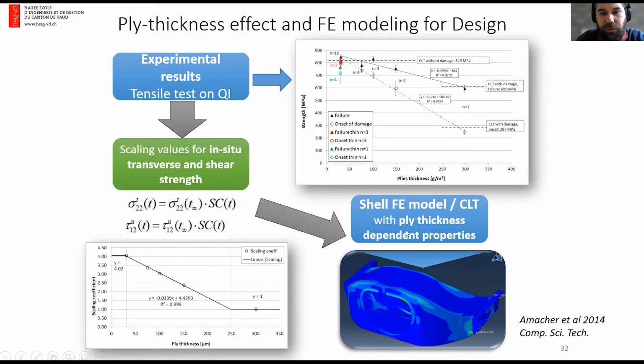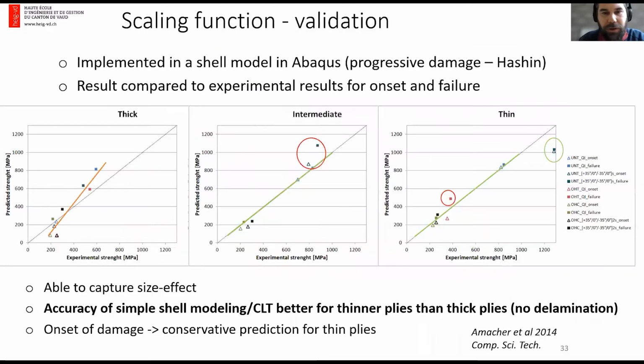Then introducing this in a standard shell element with, for example, a matrix failure criterion can work to predict the performance of Thin-Ply fairly well, at least until the onset of damage. Here we did simulate many different conditions, like a notched tension test, a notched open hole tensile test, and open hole compression for different laminates using simple shell theories.